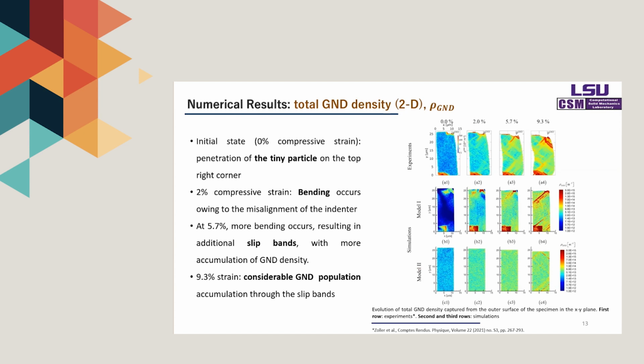For the initial state, it is noted that the penetration of the tiny particle on the top corner, that you see here, produces a high accumulation of total GND density.